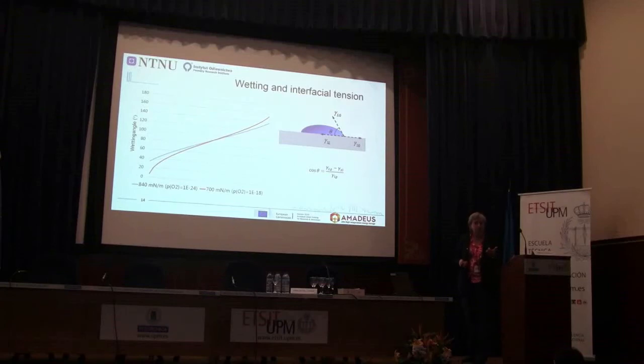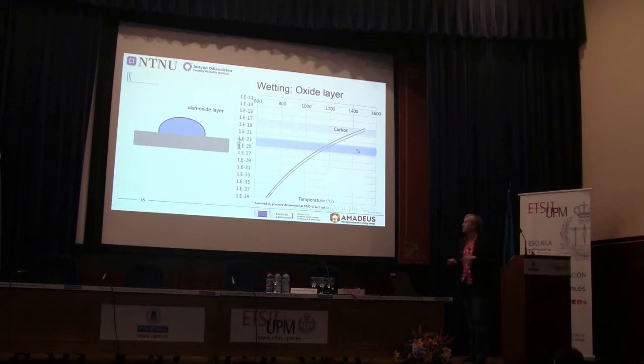However, the oxygen pressure will maybe have a more important effect on the skin oxide layer. So if we have a substrate here and we have a drop of our phase change material, we may have a skin oxide layer. And this is very typical for silicon and aluminium. And this is very, very thin, so it's very hard to detect it.